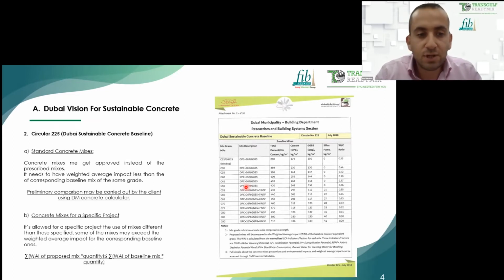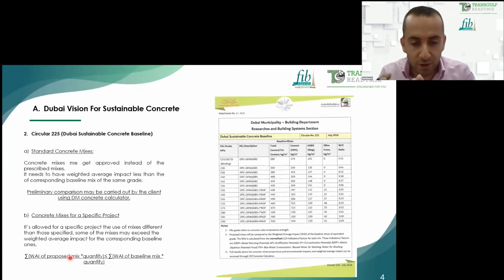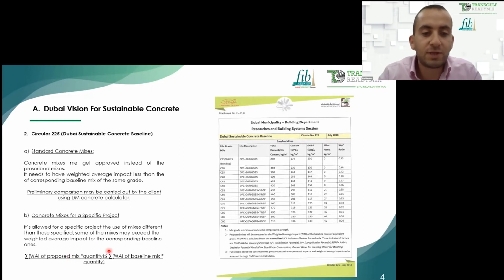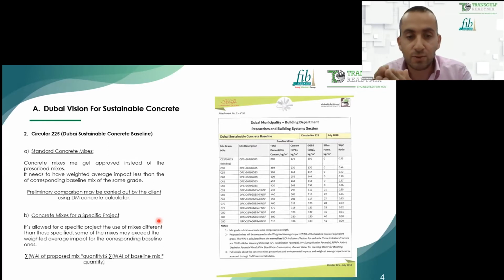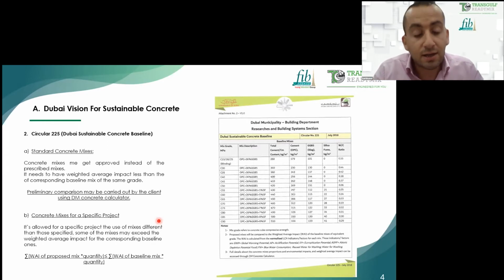This is one option. The second option is for a full, specific project. What we need in this one is an accurate BOQ, bill of quantity, for all the mixes, and we calculate the weighted average impact for each mix. The weighted average impact of each mix multiplied by its quantity, summed for all the mixes, must be below the weighted average impact for the corresponding mixes from the baseline multiplied by the same quantity. As long as the summation of the weighted average impact is below that of the corresponding mixes in the municipality baseline mixes, it can be approved.